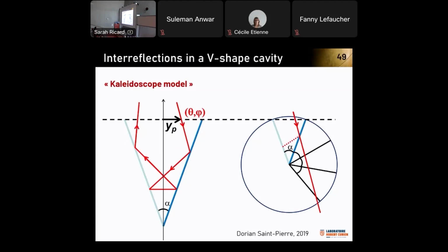Okay. You need also to consider diffuse lighting, not only directional lighting as you proceed. That's also something that I did not insist on, but when you look at metallic objects, if you have only light that comes from one direction, you either see the light in the reflection direction or it is black. So of course, a metallic object shows its complete appearance under a diffuse lighting. This is what is assumed here. Whatever your position, you always have light rays that are reflected.